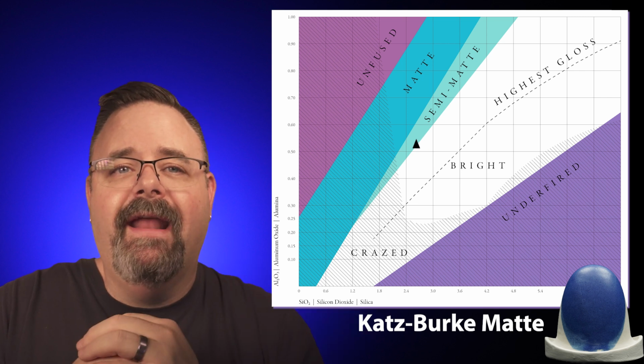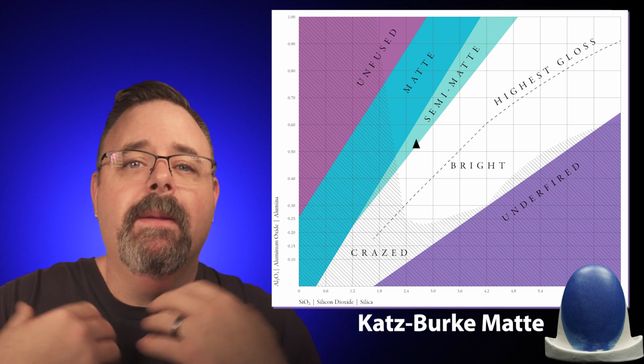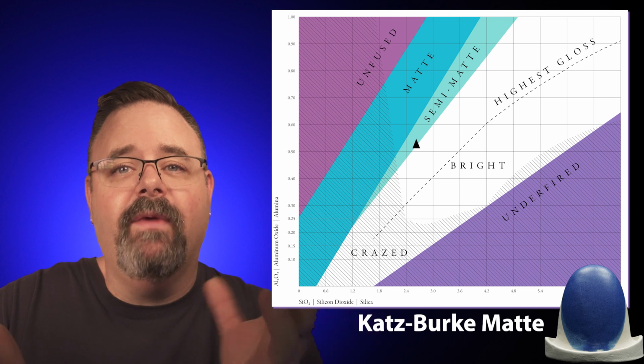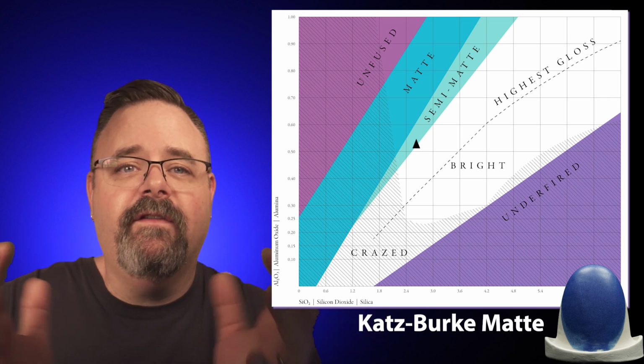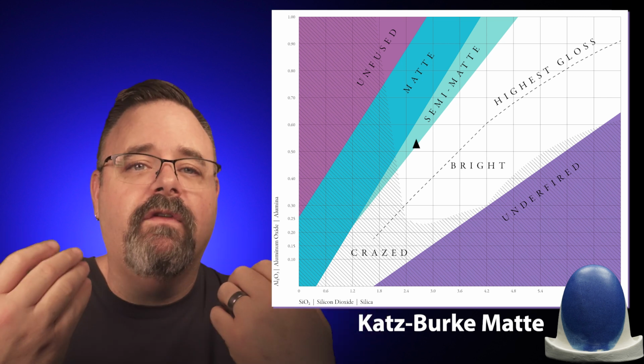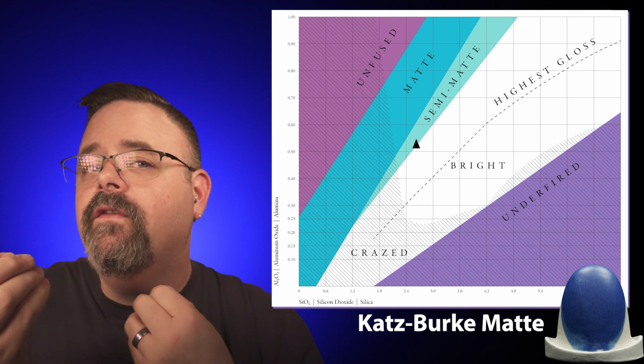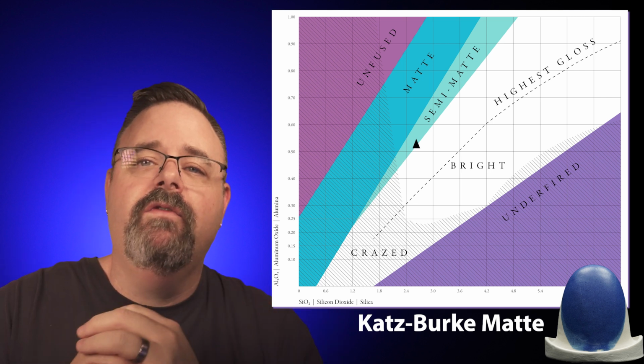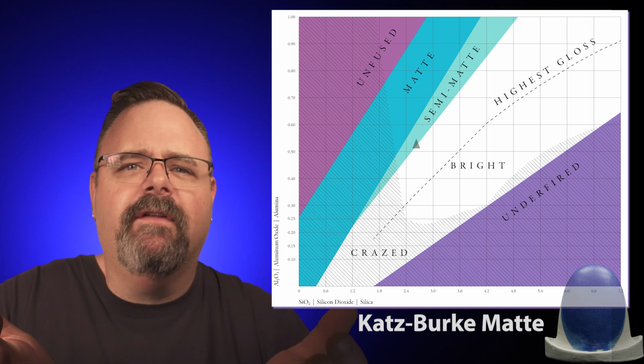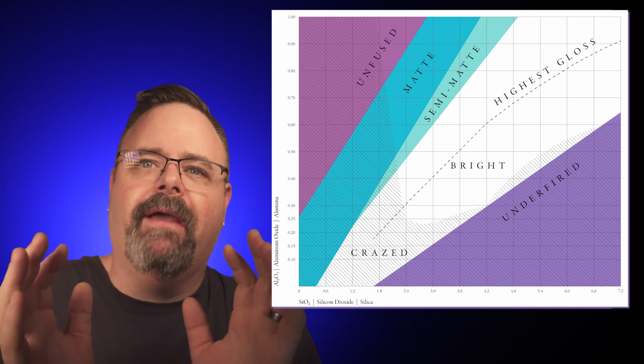So when we look at the Katz-Burke matte here and we plot it on Stull's map, where is it? Right there on that edge of the matte semi-matte region, meaning that we have a true matte glaze. We have created that crystal inside of our glass, which is going to give us the texture, but also the durability of a true matte glaze. Now, how do we know what that crystal is? We have to get a little bit nerdy about it.